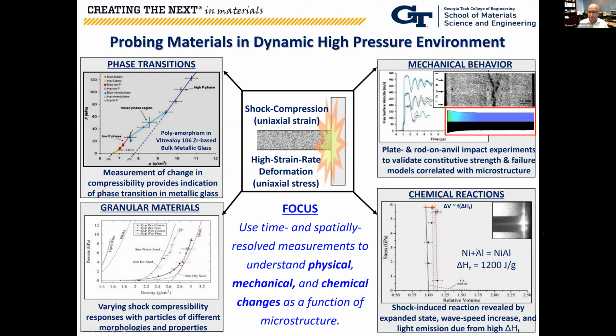These are very highly exothermic reactions. And again, on the basis of measurements of stress and relative volume, density is not directly measured, but you can calculate that from shock or particle velocity measurements as well. You plot those in this type of a map, and when you see deviations from what you would otherwise consider without any changes taking place, those deviations are inferences for chemical reaction or phase change taking place.